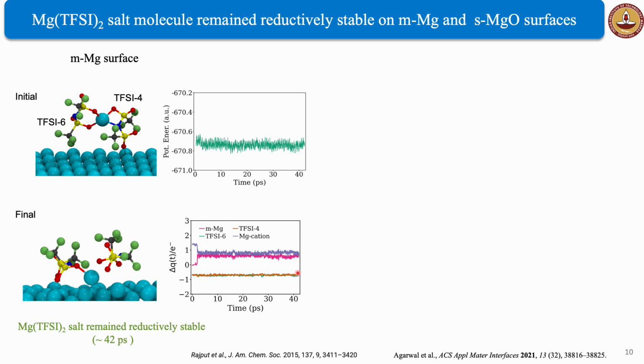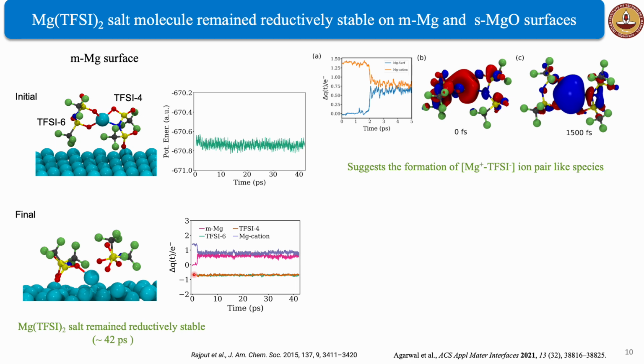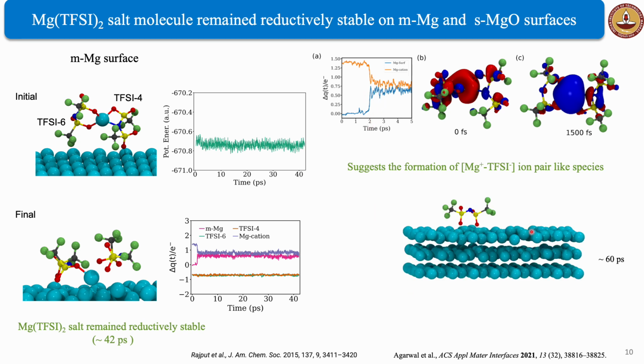Next, we analyze the time-dependent charge transfer, as electrolyte decomposition is often triggered by interfacial charge transfer. Here, we observe that within the first 2 picoseconds, there is a charge transfer of about 1 electron from the metallic Mg surface to the Mg2+ cation. This preferential charge transfer to the Mg cation rather than the TFSI anions could be attributed to the localization of the LUMO over the Mg2+ cation. After the charge transfer, there is a formation of Mg+ TFSI- ion-pair-like species, and these species remain reductively stable for the rest of the simulation, and there is no further charge transfer from the surface to the salt.